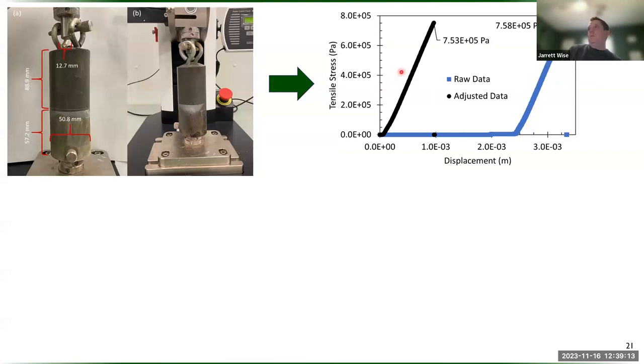So that's what we were looking at, in which we developed a testing model to basically just have a piece of steel bar with cement cured on top of it for 2 days. We know that's unrealistic, but time is money, and 2 days is a long time to wait when you're trying to test. And then we just hook the steel to the plate and hook the cement to the tensile tester and just pull it apart, in which we can measure the force required to pull it apart, and we know the distance it's pulling. So this is some of the data where this blue is the raw data where all of a sudden it starts to pull and then it snaps and breaks.